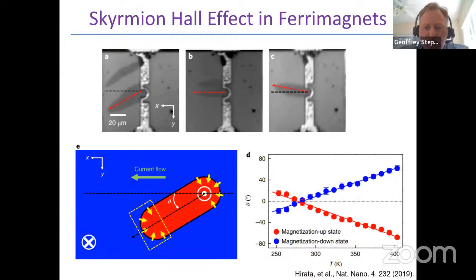And so this was shown in a very nice paper a couple of years ago, looking at a magnetic skyrmion or a bubble and looking at the expansion of this. So it's not a translational motion, but nonetheless, a dynamics that can be understood in terms of a control of the skyrmion Hall effect, in this case by temperature. And so all of these bode well in using ferrimagnets for applications in devices.